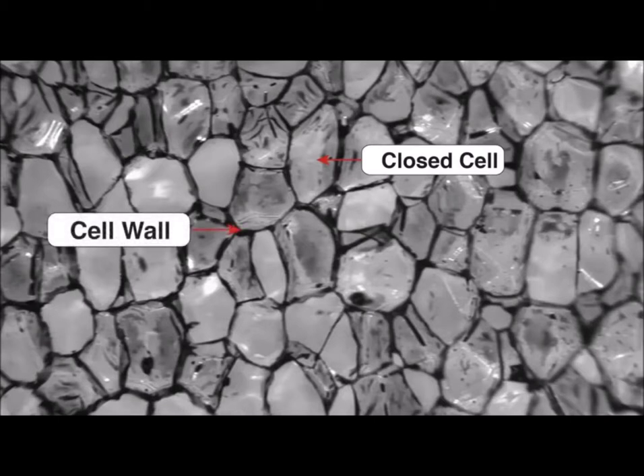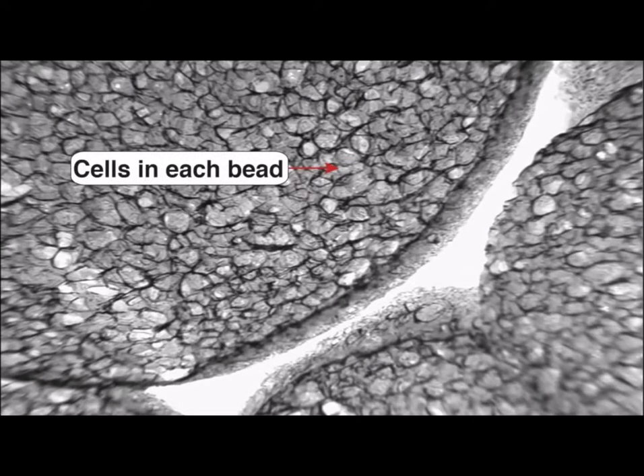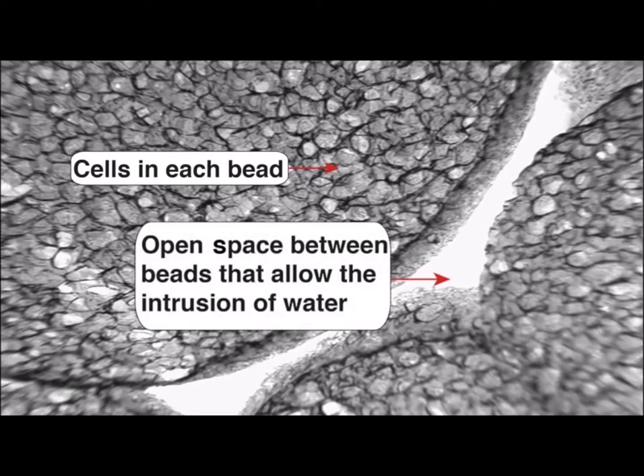With the XPS continuous extrusion process, a homogeneous closed cell matrix is produced through the entire cross section of the foam. This matrix of closed cells resists water penetration, and that's important because water penetration can reduce R value if absorbed into the insulation. With the EPS cell structure, the bead molding process leaves voids between beads where water can enter. Although the individual beads of EPS are closed cell, the voids between the beads can absorb water, which reduces the already lower in-service R value of EPS.